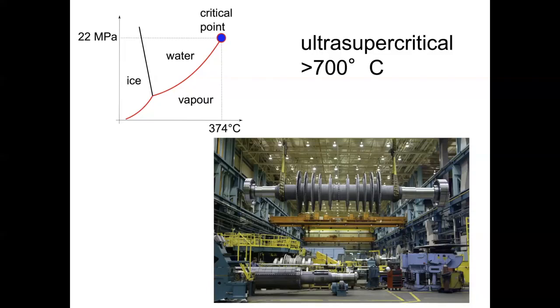Okay, so I'll begin by saying that there is no steel which can survive a temperature of 750 degrees steam temperature, 100 megapascals stress, and a 40-year lifetime. A huge amount of effort has gone into this to try and push the limits of ferritic steels to 650 degrees, and they haven't succeeded. The maximum we can get to is 630 degrees.